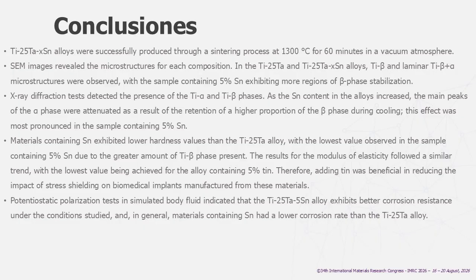The X-ray diffraction test detected the presence of titanium alpha and titanium beta phases as the tin content in the alloy increased. The main peaks of the alpha phase were attenuated as a result of the retention of a higher proportion of the beta phase during cooling. This effect was most pronounced in the sample containing 5% tin.